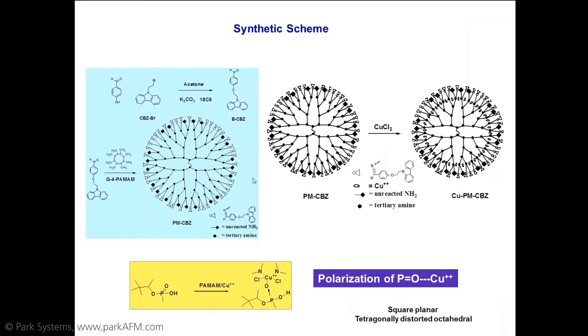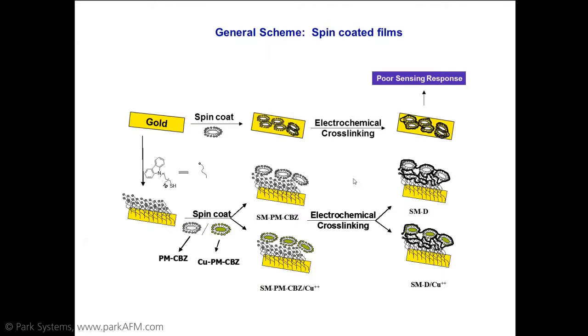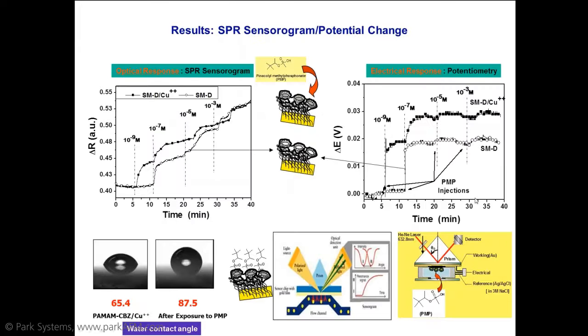So the procedure is as follows. Here you can see the dendrimer was modified with carbazole reactive groups, then doped with copper or impregnated with copper. The idea is that copper actually helps in complexing the analyte on the surface of the dendrimer, and then we electropolymerize the dendrimer on top of an SPR chip or gold surface. We did several variations. One is we simply spin coated the material and then electrochemically crosslinked them on the surface. The other is we actually modified the surface of gold with a carbazole unit that is then used to electropolymerize and complex with the dendrimer, leading to two types. One is an electropolymerized sample without copper, and another one with copper. And you'll see later the differences in these measurements.